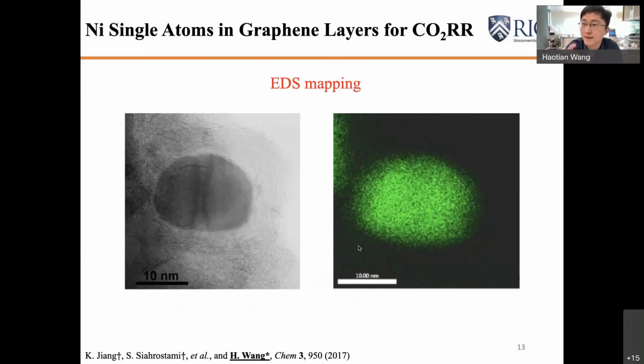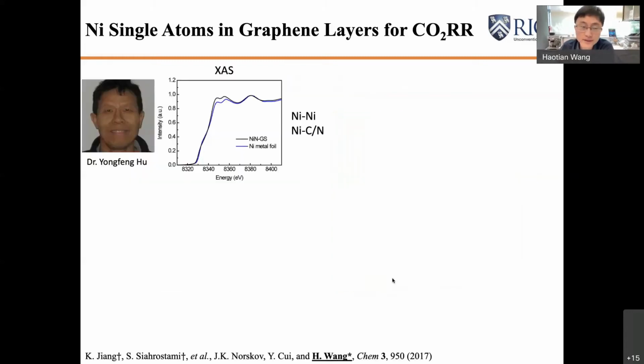We can use the TEM mapping technology, the EDX mapping. So we can see the nickel signals coming from the nickel nanoparticles are very intense in these regions. But away from that, into the carbon-rich areas, we do still see a lot of nickel signals. So that actually gives us the confidence that we indeed trap a lot of nickel atoms in the carbon areas, in the graphene areas. And then comes the second question, whether they are in clusters or in single atomic sites. This is a very difficult question at that time for us to answer.